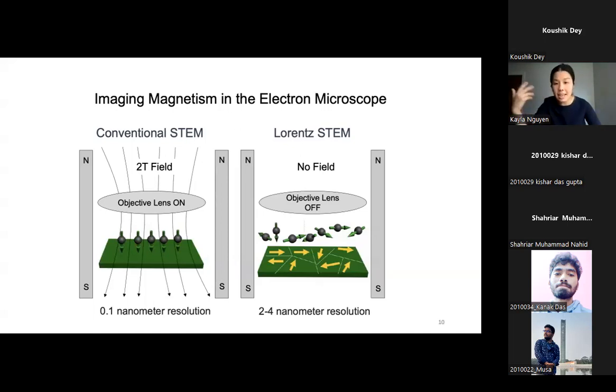And so this lens actually applies a field that is 2 Tesla to your magnetic sample. And because you're applying a field that is 2 Tesla, all the spins of your sample get aligned to the field of the microscope. This is not what you want. What you want is to image the intrinsic field of the sample. And so what you have to do is you have to turn off the objective lens. And so now you're looking at the intrinsic field of your sample.